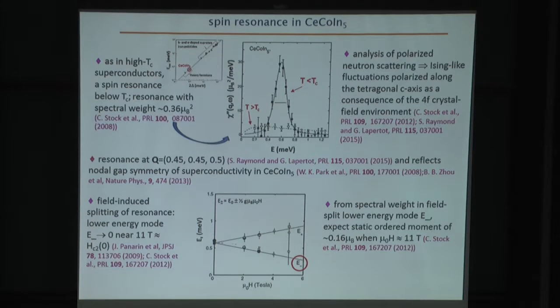Now, if we apply a magnetic field, this resonance splits into two modes, a higher energy mode and a lower energy mode. And the magnitude of this splitting is given, again, precisely by the g factor of the cerium crystal field doublet ground state. So it's a long extrapolation, but if we take the bold assumption and continue this energy versus field plot to zero energy, this lower energy mode should go to zero energy in a field of about 11 Tesla or so. And as we'll see, this is very close to the upper critical field of cerium-cobalt-indium-5. So let me just say again what this means.